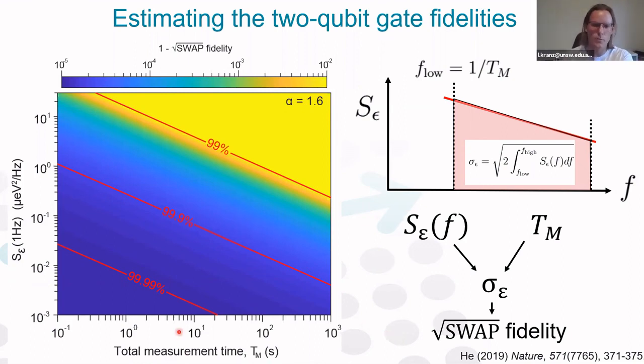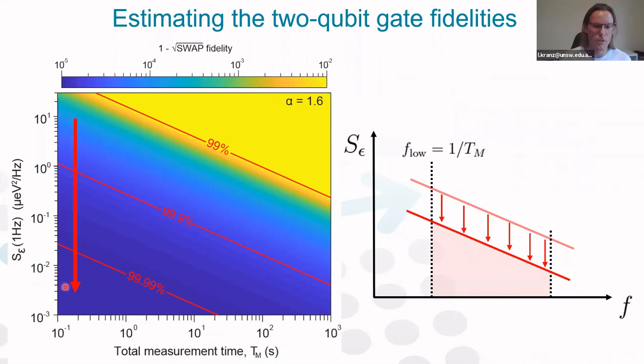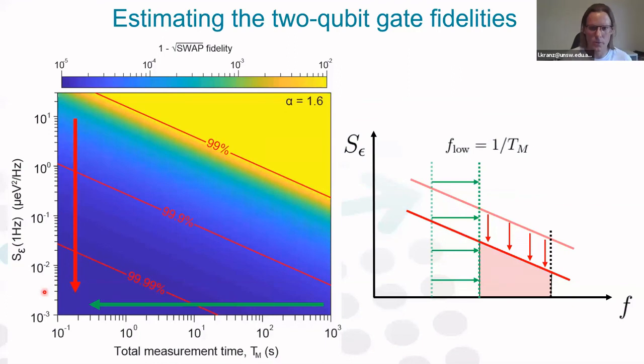So what we can see from our modeling is that to reach this desired high fidelity two-qubit gate region, we have to first of all have really low noise in our device, which we hope we can achieve with our crystalline environment hosting the qubits. And on the other hand, we need to be able to perform our experiments as fast as possible, so as to reduce the total measurement time and to avoid these low frequencies of noise.